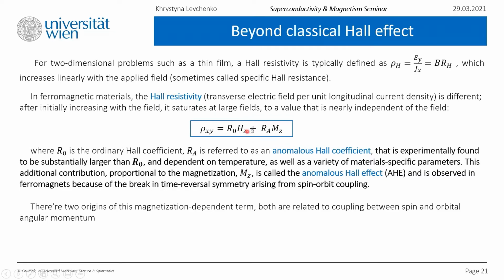You see, when the magnetic field is still weak, the resistivity will increase sharply until it reaches some saturation point. The magnetic field is then strong enough, and there will be a plateau. So this equation describes the case for a ferromagnet. And the first term in it is the classical Hall effect. It's linear in field, and it is the term that determines type and concentration of free carriers.